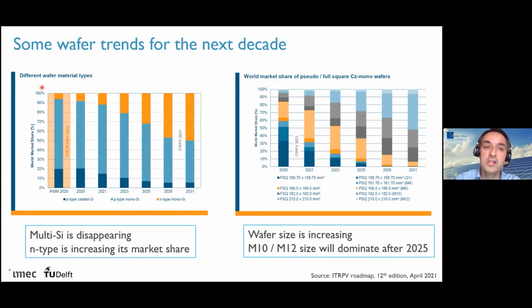So far I've mostly focused on monocrystalline silicon wafers. The reason is that although in the past, until a few years ago, at least 50% of PV panels were made based on multicrystalline silicon - this is the dark blue here - we see that in 2021 the amount of multicrystalline silicon cells still being processed is actually below 20%, and it's foreseen that it will more or less disappear in the coming years.